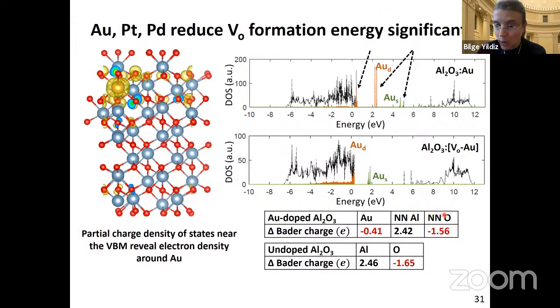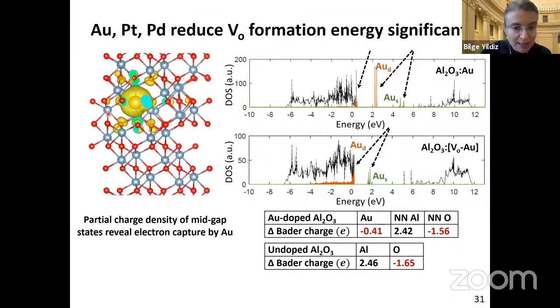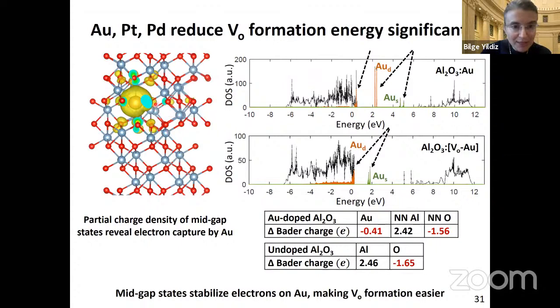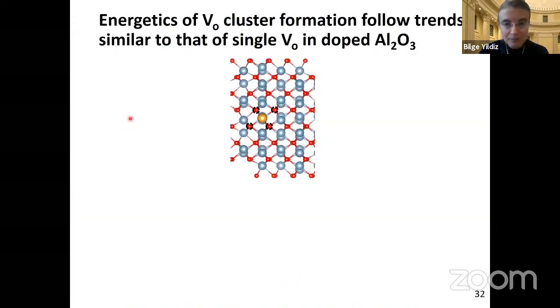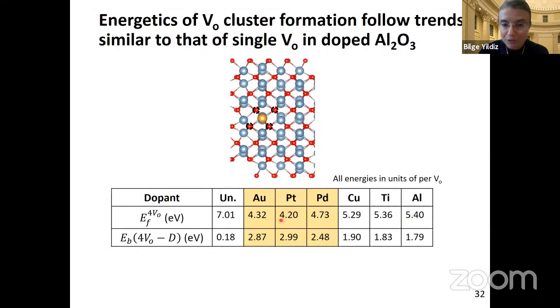Okay, so on one hand, that lowers the aluminum oxygen bond strength and makes it easier to remove the oxygen. But even more importantly, it's gold that picks up the electrons after removing the oxygen. And we can see that in this partial charge density of gold states after forming the oxygen vacancy, which are really picking up that excess electron and not having to deal with forming an F center, and that substantially reduces the energy to create oxygen vacancies. And not only individual vacancies, but we can also form vacancy clusters, which is important in forming networks or filaments of conducting paths made of vacancies. So vacancy cluster formation, as well as vacancy cluster binding around these metals, becomes more favorable when you're dealing with high electronegativity elements.